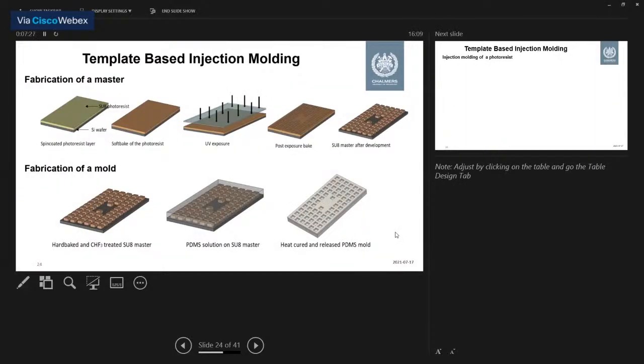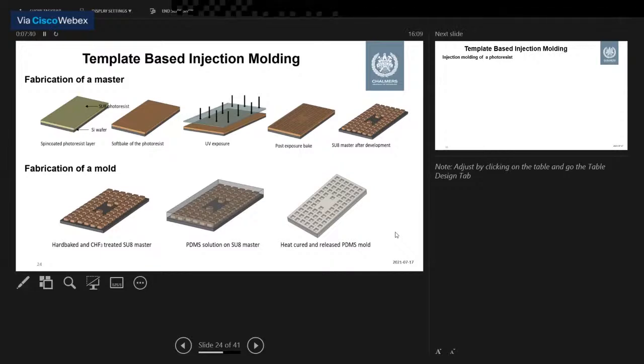So first, to fabricate a master, we choose SUEX photoresist because the antenna that we fabricate is for D-band at 140 gigahertz. So the thickness of the layers which is needed is very thick, and only SUEX photoresist can provide this type of thick structure. So we use SUEX photoresist. We repeat the process steps that I mentioned before, like soft baking, spin coating, soft baking, UV exposure, and you can see during post-exposure bake, we get some area cross-linked and some area unchanged. And when we develop it, we get the final master.